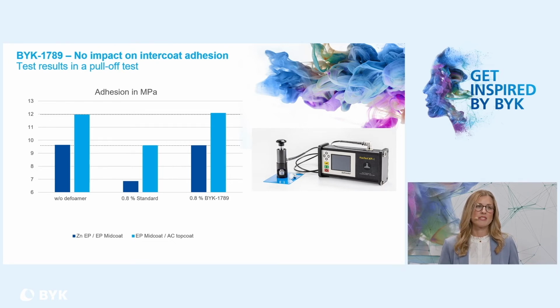So the use of a standard silicone defoamer, in this case, really lowers the intercoat adhesion. The intercoat adhesion was tested in an epoxy midcoat to a zinc-rich primer, as well as to an acrylate top coat. And we incorporated the silicone defoamers at a relatively high dosage of 0.8% in the epoxy midcoat. And as you can see, although BYK-1789 is also based on silicone technology, it does not show any negative impact on the intercoat adhesion.